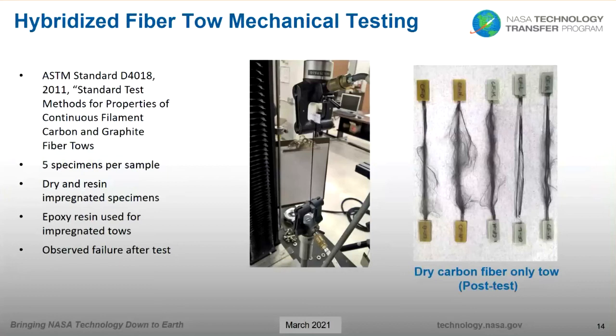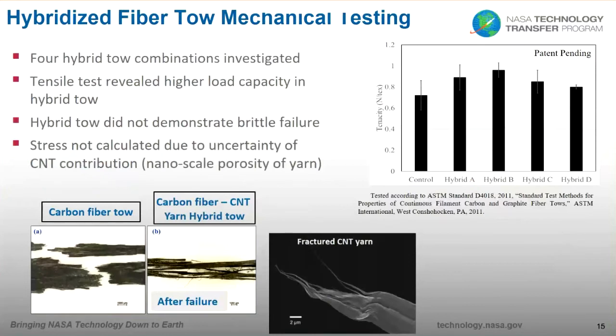But since we made a change to the tow construction, I thought that it would be a good idea to see if we could observe any influence of the carbon nanotube yarns on the mechanical behavior of the dry fibers. So fibers without resin were looked into as well. And an untoughened epoxy was used to infiltrate the tows, and failure of the tow was observed after tensile testing using optical microscopy.